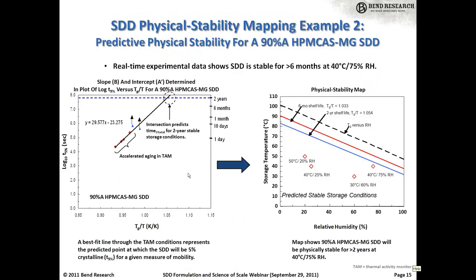Here's one more example. This is with actually a 90% active dispersion. So this was a very high Tg drug that allowed you to have a much higher loading and still maintain a high glass transition temperature. Same kind of methodology was used to make a map here of physical stability. You can translate that over into a Tg, a storage temperature, Tg versus RH kind of plot, and predict that in this particular case you will have 2 years or greater stability at even the most aggressive conditions.